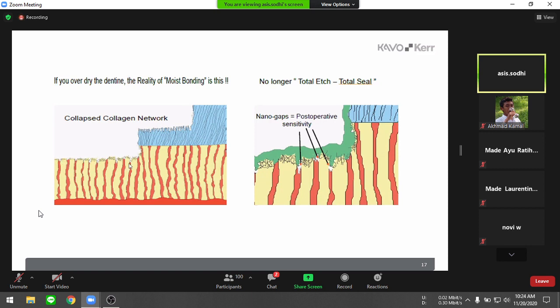Now, what happens on the dental surface when we use a total etch bonding agent is that you're dissolving the intertubular dentine. So you have gaps formed here. And then there is a collagen network, which is exposed, right? Now, collagen is like your hair. If the doctor applies a lot of air pressure on this surface while they're drying the surface after etching it, the collagen fibers can collapse. Now, as the collagen fibers collapse, the bonding agent is going to sit on top of the dentine surface.